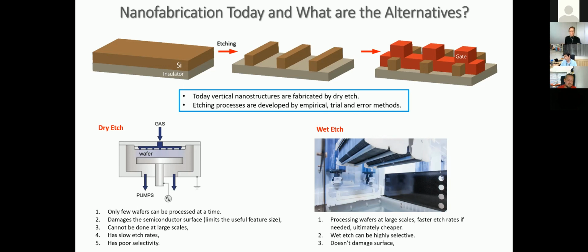But the problem is this: you can only process one wafer at a time. This is one thing. And when you're bombarding it with the ions, you damage the surfaces. If your transistor is 7 nanometers or 5 nanometers, it's all surface. If you even damage 1 or 2 layers, you're damaging the entire device, right? So that's why this is one of the disadvantages of this dry process.